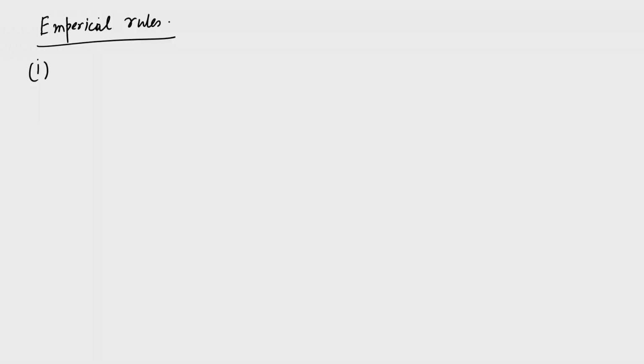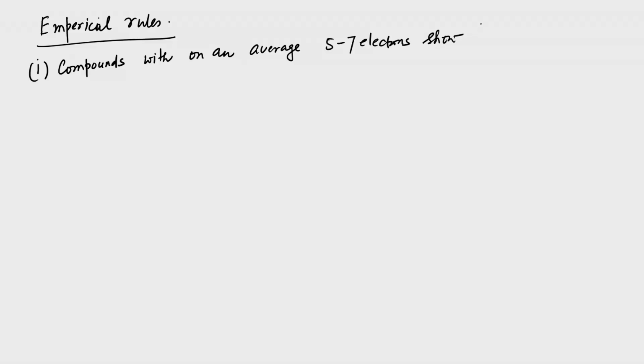It is found that compounds with, on an average, 5 to 7 electrons show larger TC. An example is ruthenium molybdenum, which has, rather, 7 electrons on average.